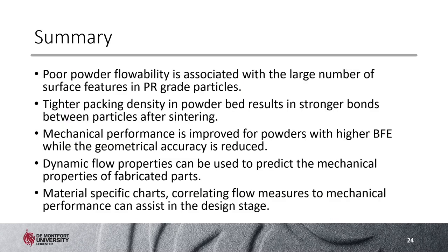To summarize: poor powder flowability is associated with the large number of nano-sized features on the surface of print ready particles. For powders with tighter packing density, stronger bonds were formed between particles and the mechanical performance of parts was improved. However, for powders with improved flowability and tighter packing density, the geometrical accuracy was reduced. Dynamic flow properties can be used to predict the mechanical properties of parts, and material-specific charts can be generated to correlate flow measures to mechanical performance, assisting in the design stage to tailor powder according to the mechanical performance needed.